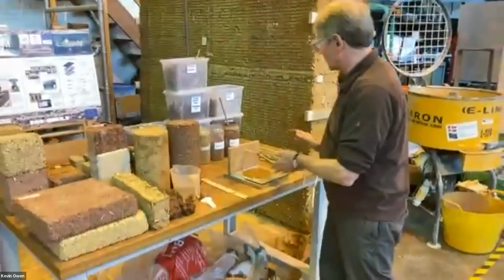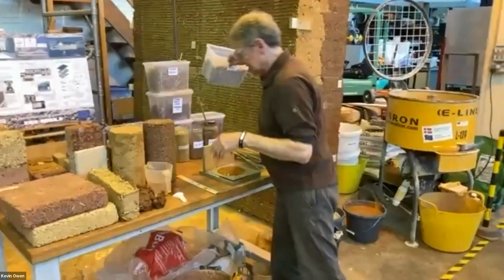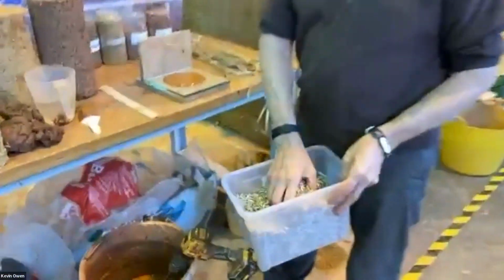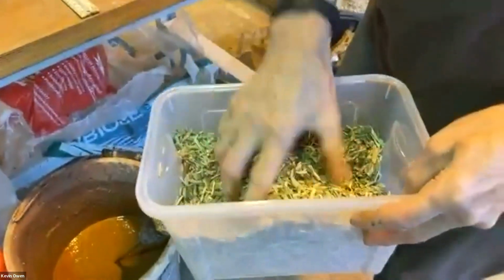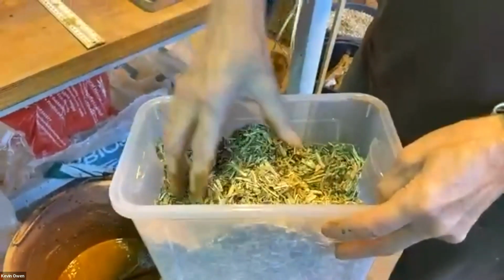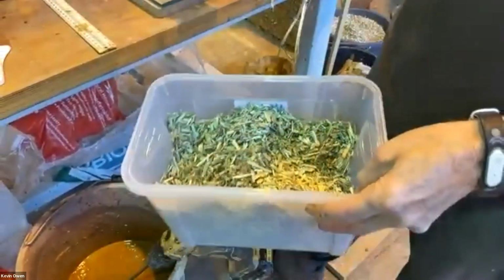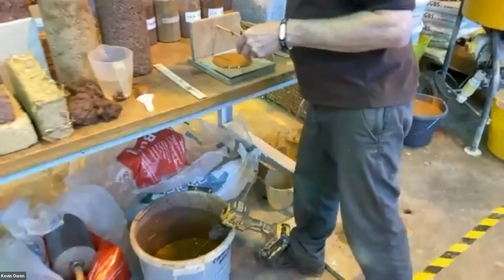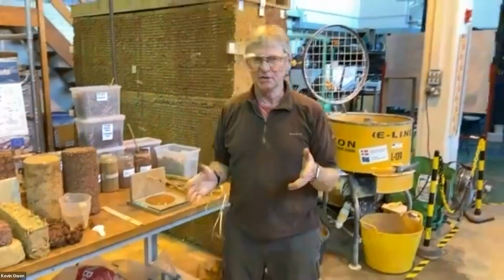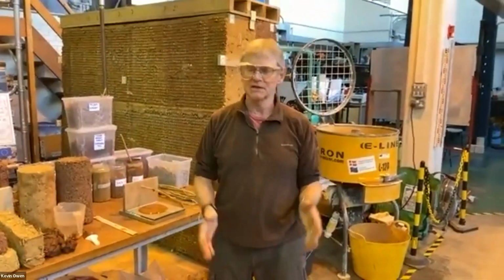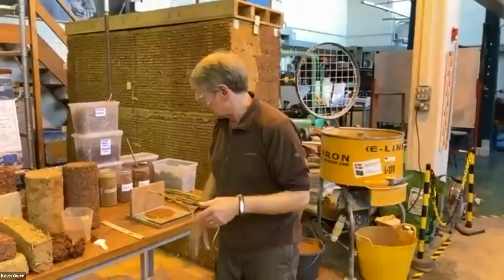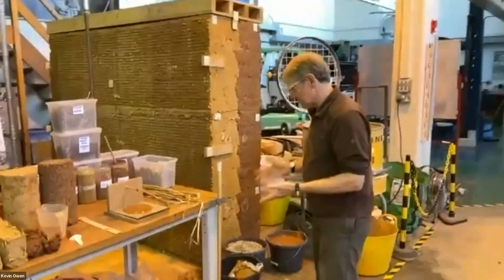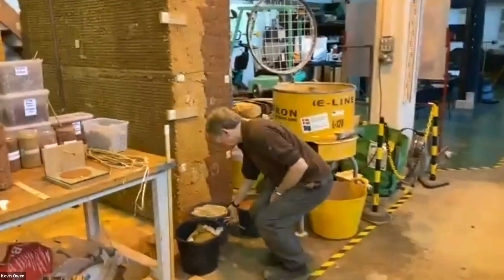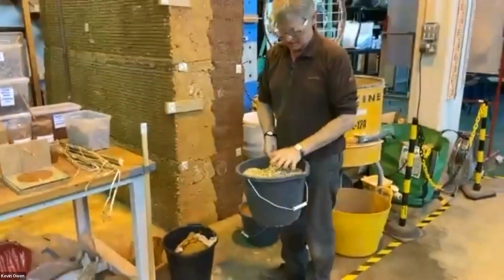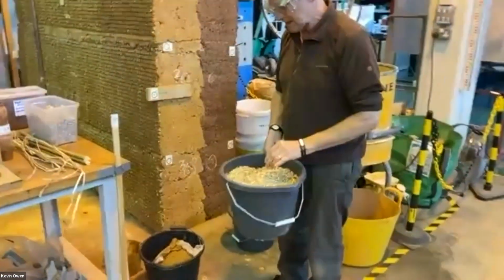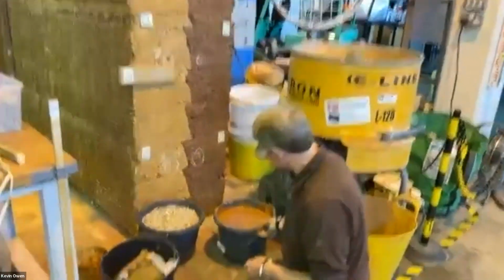And all we then need to do is to add our thermal insulative material, which is the hemp shiv. And that, by weight, is 50% of the dry weight of that material. Now, if you're on site, you're not going to be weighing things. You want to know what the volume is. How many bucketfuls or tubfuls does it take? So we've calculated that the right mix would be 3 buckets or containers of the shiv. So by volume, that's 3 and 1 of the slip.